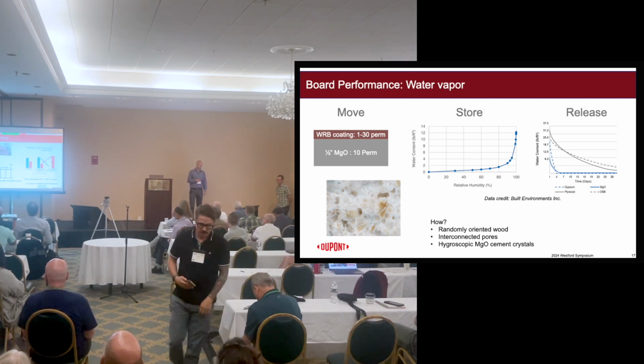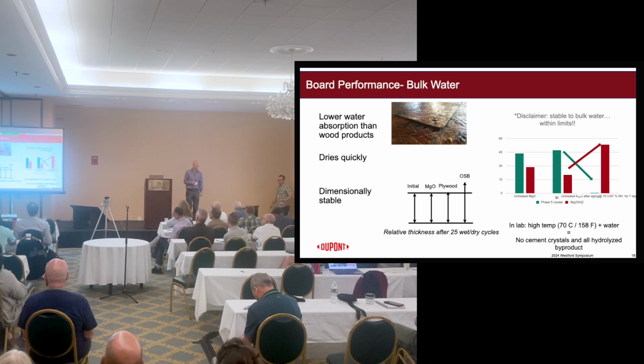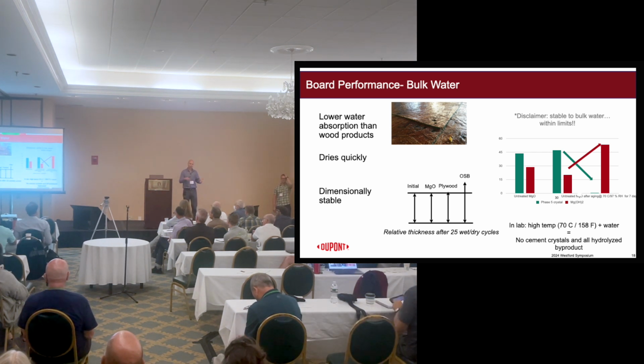Last thing, starts to get a little bit towards the box that I've been talking about. It is stable to repeated wet-dry cycles with bulk water. On the bottom left here shows a graph of what you'd expect the dimensional stability of this to be after a number of wet-dry cycles, showing that MgO, even after it's been wet and dry 25 times, is still functionally the same size as when it started, compared to the well-known phenomenon that OSB continually gets thicker and thicker because of the movement of the materials inside as it swells and then shrinks again.